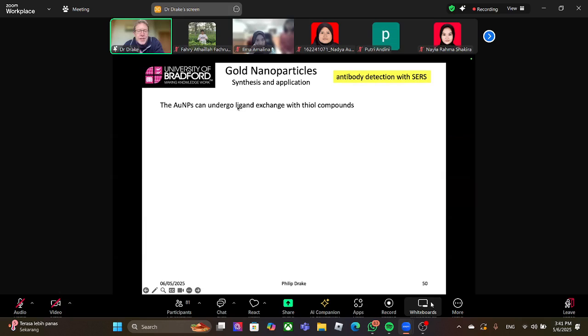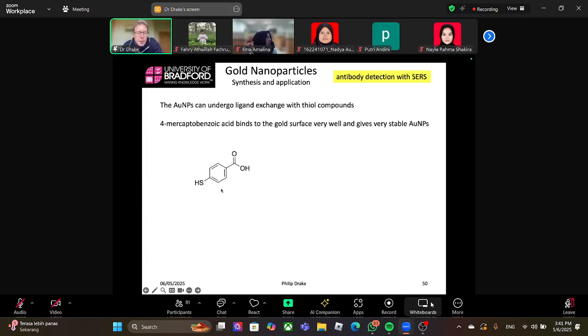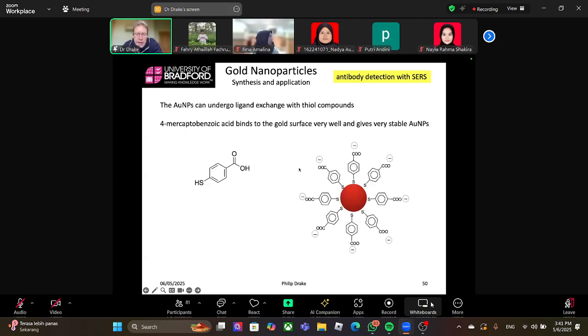So gold can undergo ligand exchange with thiol compounds. Mercaptobenzoic acid binds to the gold surface very well and gives very stable gold particles. Anything with a thiol in will always bond to gold nanoparticles. Mercaptobenzoic acid has a benzene ring, carboxylic acid group, and a thiol. Mix that with gold nanoparticles, you get a negative charged surface, very well stabilized, with a sulfur attached to the gold.